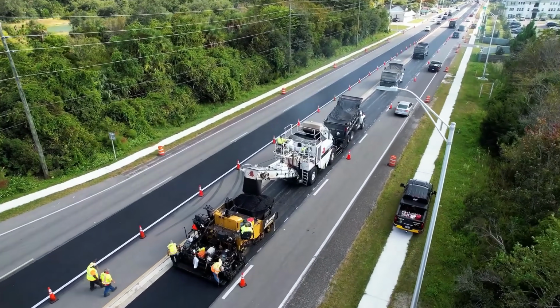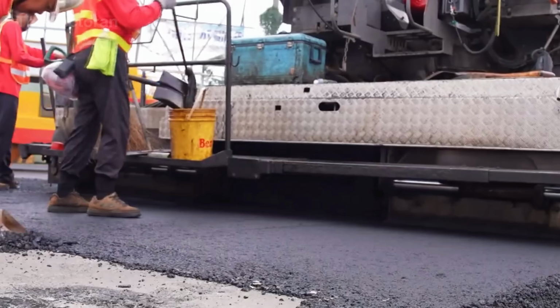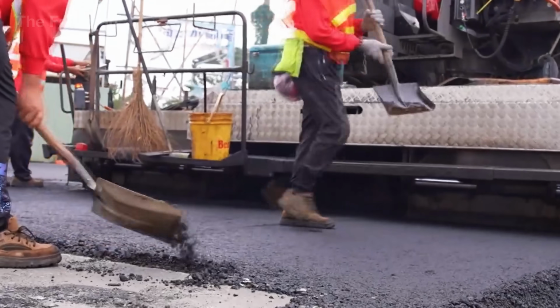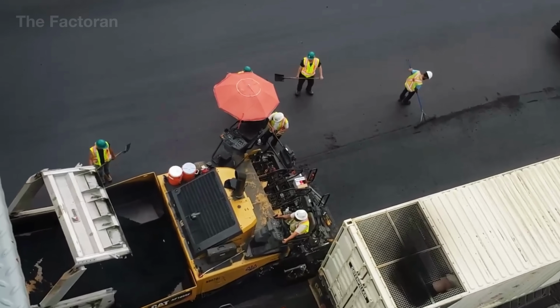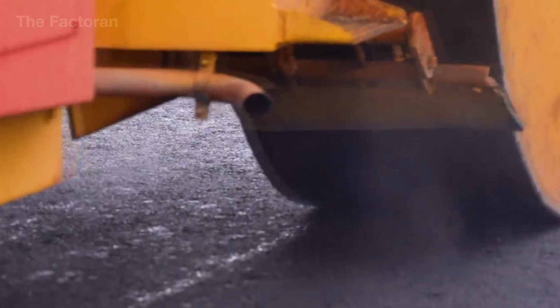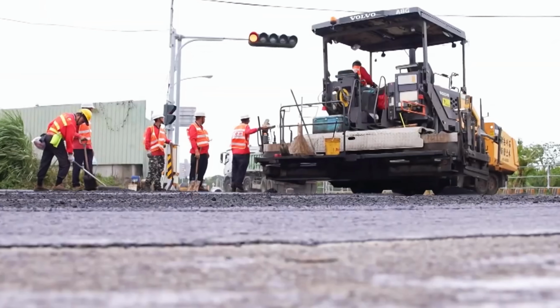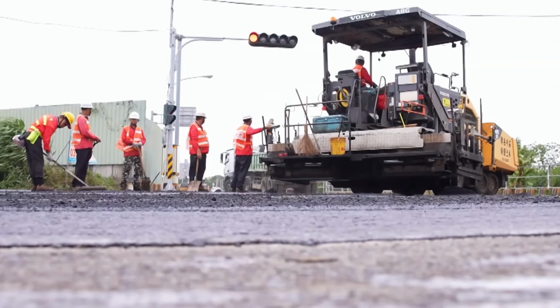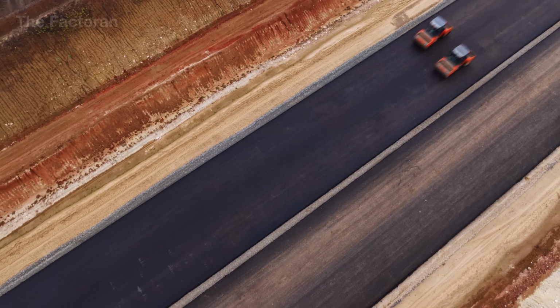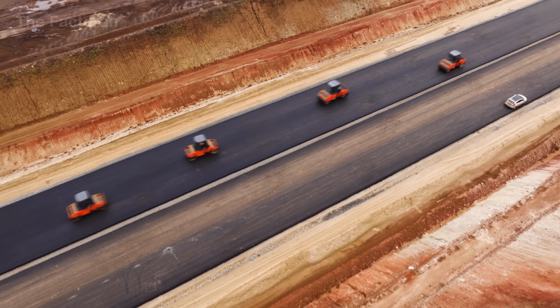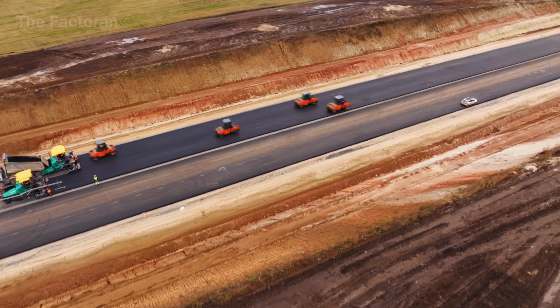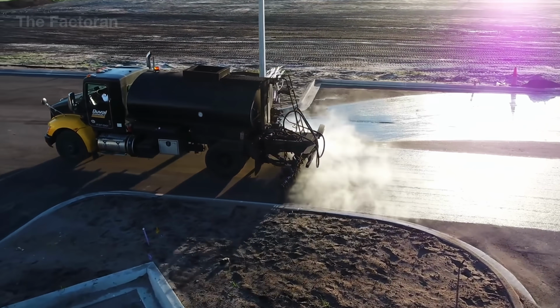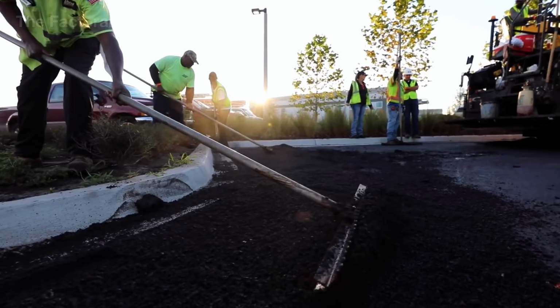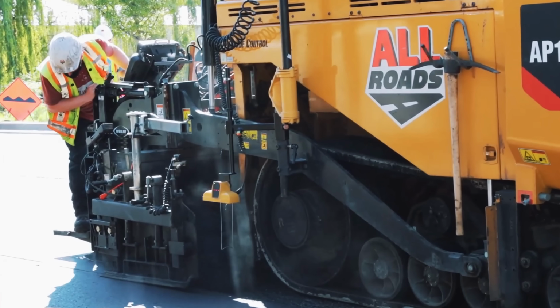First comes the smooth steel drum roller, giving the mat its initial compaction. Next, the rubber tire roller, weighing tens of tons, presses the aggregate tightly together, sealing the voids. Finally, the vibrating steel roller finishes the surface, increasing density while leaving it smooth and even. Throughout the entire process, the temperature of the mix is closely monitored because once it cools below 200 degrees Fahrenheit, about 93 degrees Celsius, the asphalt hardens and loses its ability to bond.